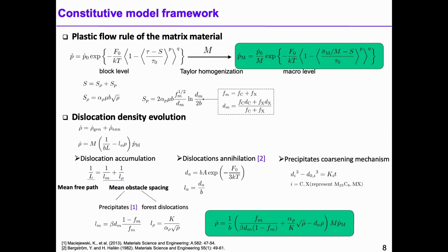For the plastic flow rule of the matrix material at block level, creep deformation is controlled by dislocation glide. We use the Taylor homogenization method to get the plastic flow rule of the matrix at macro level. The slip resistance can be divided into two parts: dislocation induced resistance and precipitation induced resistance. The dislocation density rate can be divided into two parts: dislocation accumulation and dislocation annihilation.